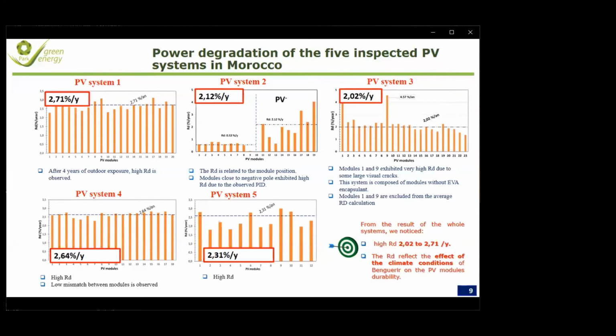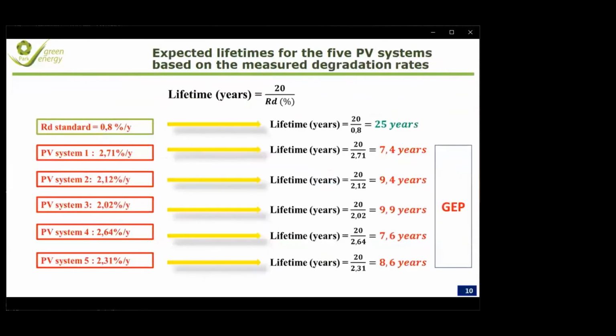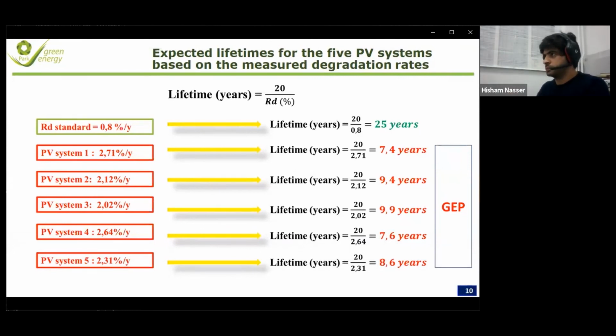In fact, the power drop in the present study is mainly related to the harsh climatic condition of the studied operating site. In addition, the high degradation rate reflects the relatively low expected lifetime for the module, as the manufacturer gave about 25 years as the lifetime of the PV module with a maximum of 20% of power drop. The degradation rates found in the present study are very high. So this may influence dramatically the project development of a PV plant, especially the plant's economic calculation and payback time. So it is recommended in the present study to develop a new PV module generation, like a desert module, dedicated to harsh desert climate.